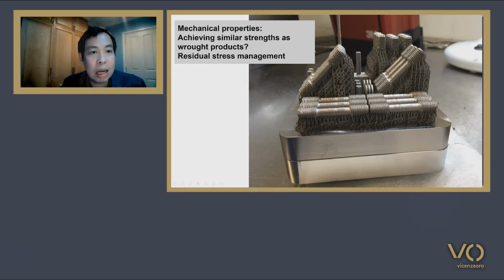Now, back to the printing of the objects. We actually have to print a lot of these because, first of all, we want to achieve similar strength as the wrought products or the investment cast products. And there are also concerns about residual stress management. This is a very big problem in additive manufacturing because of the rapid heating and the subsequent cooling of the solid forms.